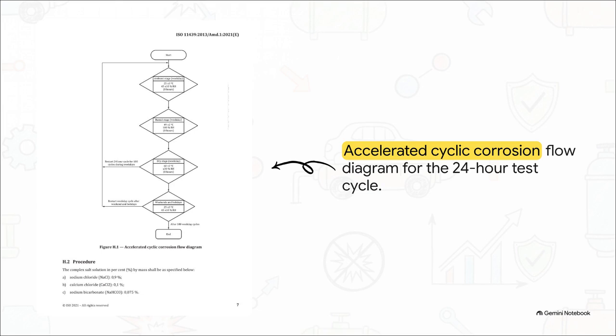Look at this flowchart. It maps out a relentless 24-hour cycle these cylinders have to endure to test their protective coatings. It starts at an ambient stage, then dynamically shifts into a 49 degrees Celsius humid stage, where moisture is just penetrating every microscopic pore, and then finishes off with a scorching 60-degree dry-off stage. And they repeat this cycle over and over again, up to 100 times, basically simulating years of harsh environmental exposure in just a matter of weeks.